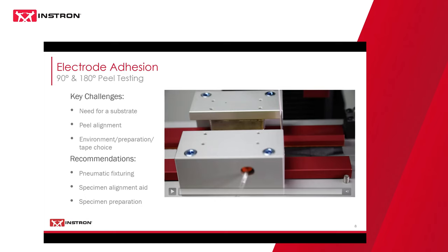But other variables to also consider, aside from the tape, would be the environment and the preparation of the material. This material can be very affected by the temperature and humidity, as well as things like the settle time of the material or of the tape curing to the material. So having a controlled environment and controlled process for this testing is also important. A lot of this data is used as a correlation between good and bad adhesion, and so you want to make sure you have the most controlled setup possible.